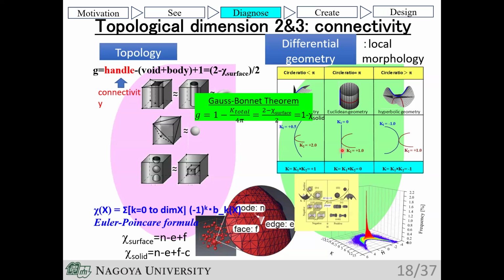At every vertex of a 3D object, the principal curvatures, maximum and minimum, are calculated to derive the Gaussian curvature K and mean curvature H. The morphological characteristics are then quantitatively mapped onto an HK plot, HK space, frequency plot. A prime example is the spheroidization of pearlite. The morphological evolution of cementite during aging can be precisely quantified by analyzing the shift in the HK coordinate distribution over time.